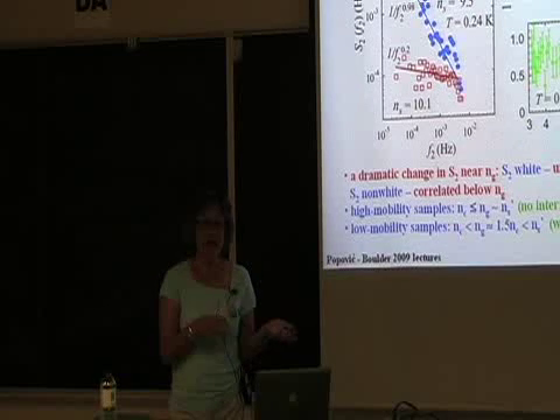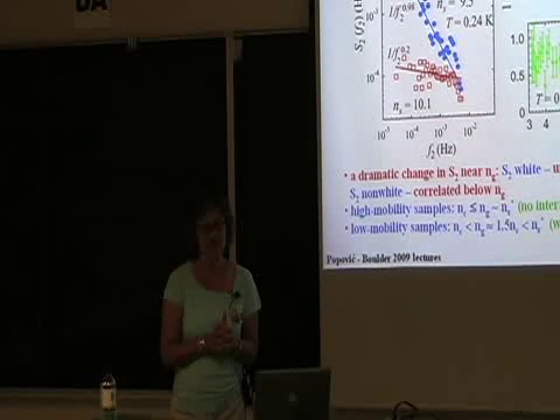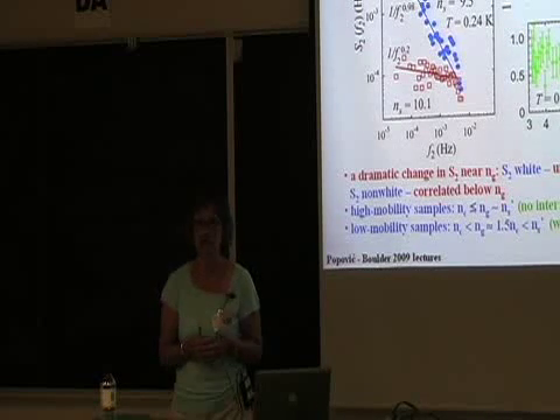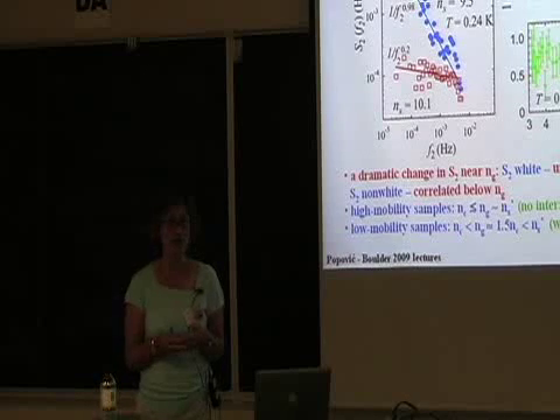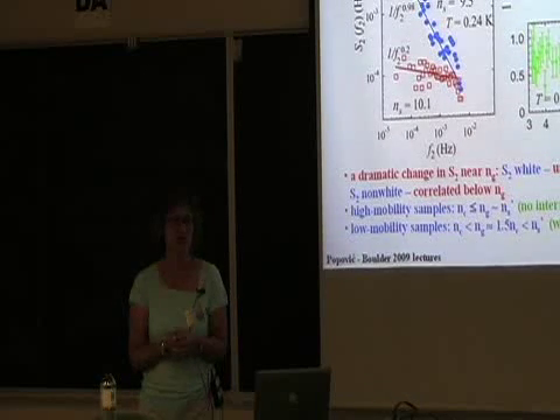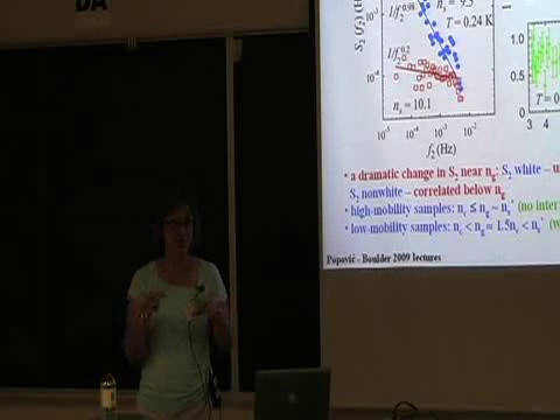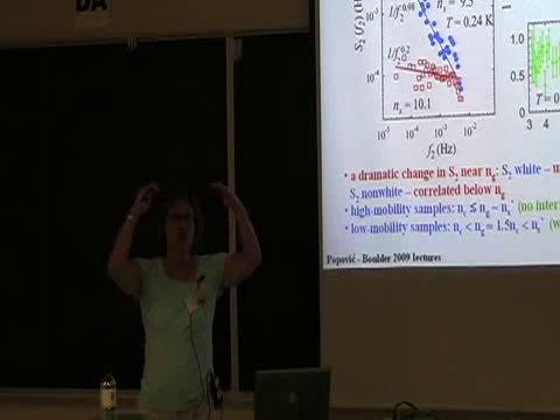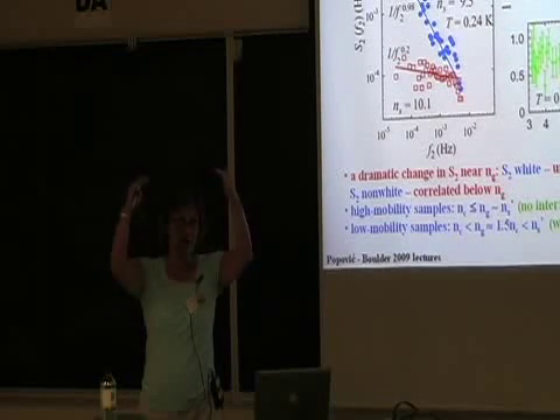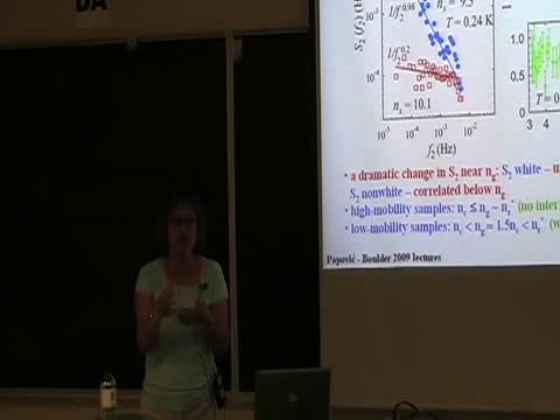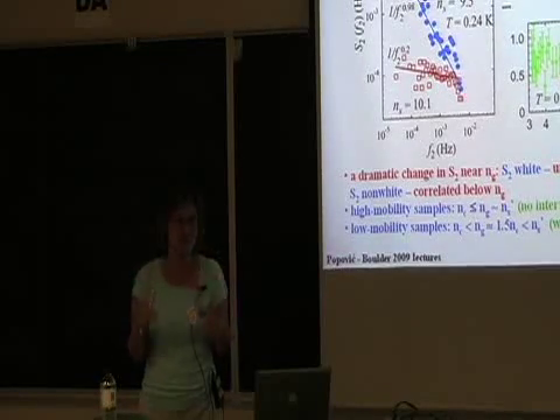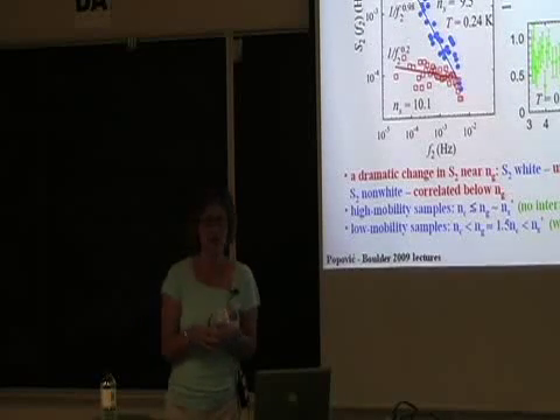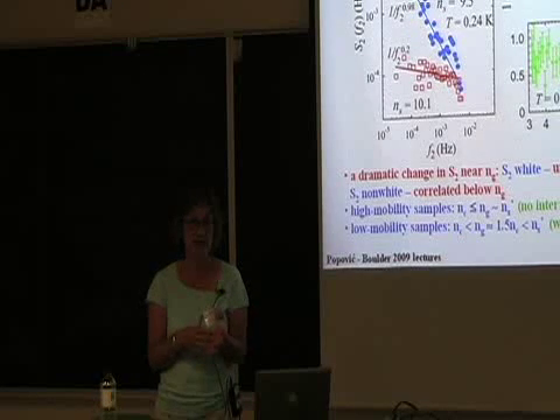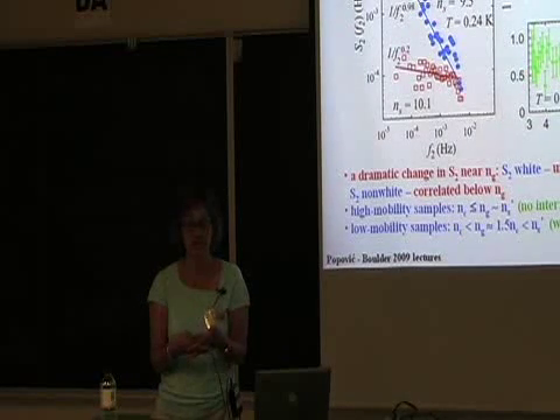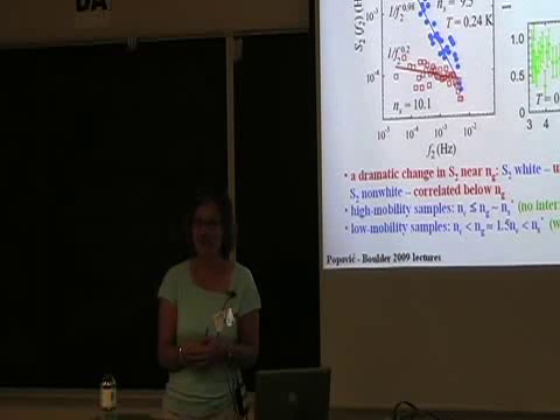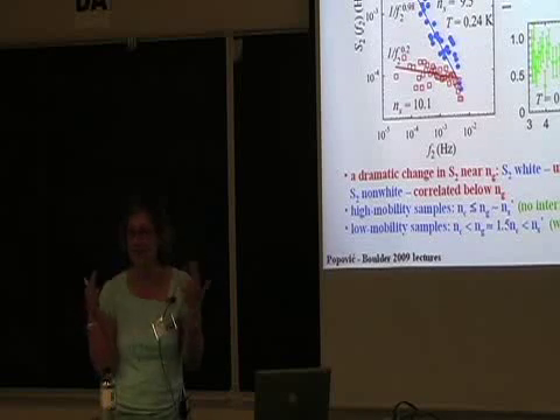So anyway, in spin glasses, Mike Weissman used the second spectra to try to differentiate between two different known models, pictures of glassy dynamics, namely hierarchical pictures and the so-called droplet pictures. In the hierarchical picture, all these states are in a tree-like structure, so everything looks the same on every time scale. The structure of the tree is the same, so there should be no dependence of the correlations. There is no characteristic frequency, no characteristic scale. Now all this was his hand-waving argument, which makes sense, but as far as I know, nobody has actually calculated this, which is a little annoying after all this time. It's been more than 10, 15, 20 years, I don't know.